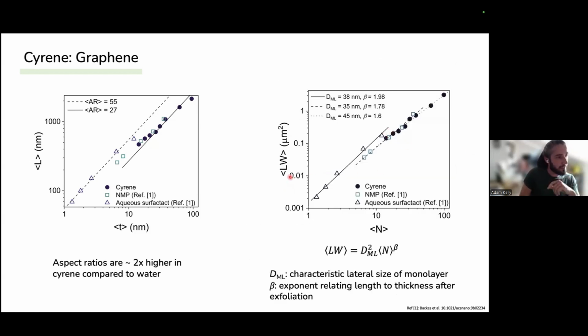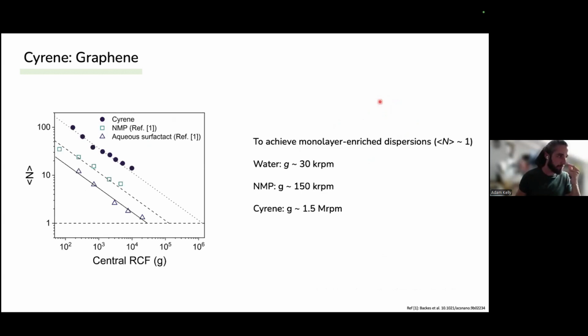Now, if we plot the area of the nanosheets here versus the thickness, we can then fit this using this equation here, which gives us the characteristic lateral size of a monolayer. Typically, this is around 30 to 40 nanometers for graphene. And then this beta here is an exponent relating length to thickness after exfoliation. And this tends to get much, much smaller then for Cyrene as it falls off compared to water. So this just gives us a measure of the relationship between aspect ratio for exfoliating in higher viscosity solvents. What we would like is a much higher beta here because this would give us higher aspect ratio nanosheets.